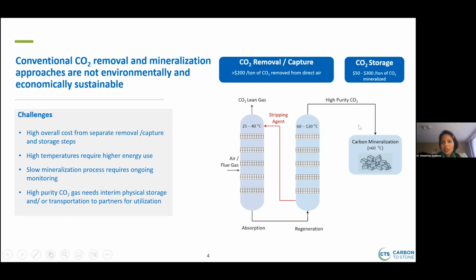The output that comes out of this regeneration column is high purity CO2, and we can now use the CO2 for further mineralization. So if we were to implement such a process for direct air capture mineralization, first, it's a multi-step process. Each of these processes occur at different temperature conditions. And if you look at the economics of this, it's upwards of $250 per ton of CO2 that's captured and mineralized directly from air. So it's very expensive.